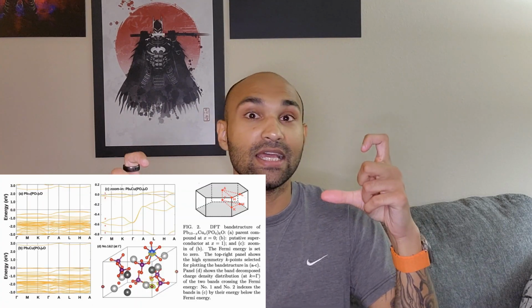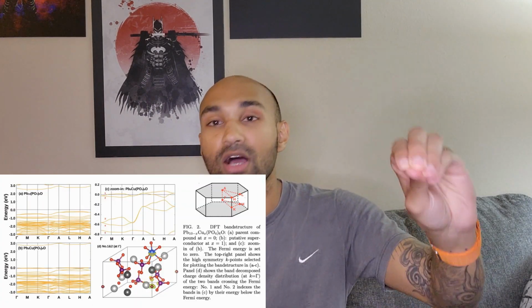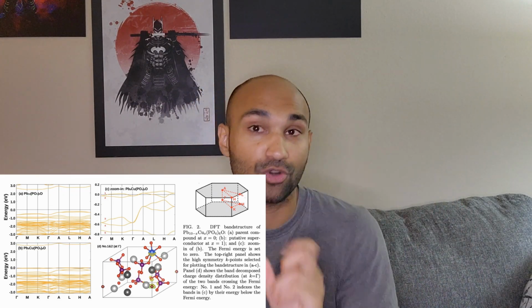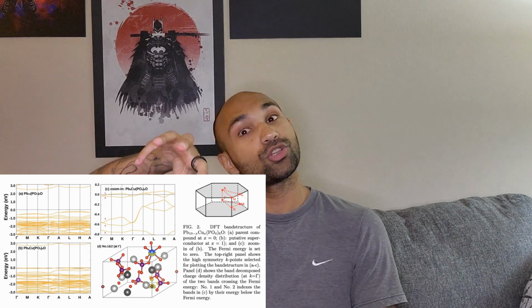However, it's not clear whether they had the copper substituting at the right lead position, which we mentioned in the last video, but to re-update here, the structure of LK-99 is like a lead apatite lattice that has copper substituted at certain points where the lead would normally be, which causes the whole structure to deform and allows it to withstand or superconduct at higher pressures and temperatures. They seem to say that they have fewer impurities, but somehow have not replicated the same properties that the Koreans are reporting. There's potential reasons for this.